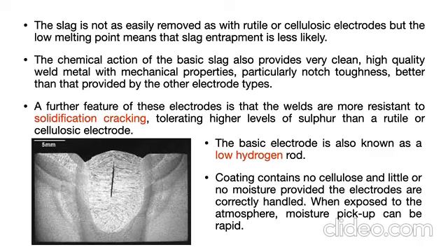Like one of the reasons will be the composition of the base metal, the composition of the weld metal formed, then due to excessive residual stresses, then due to the excessive travel speed. The other thing is due to the elliptical or tear-shaped pool of the molten metal formed.